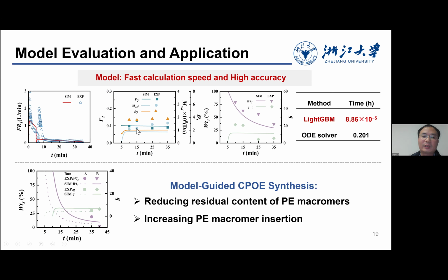You can see here we have a better match of the experiment, and the calculation results also include the molecular weights and their dispersity. And here is the weight of the residual macromonomers, and this is the insertion number of the branching chain. So finally, with this model-guided POE synthesis, we can reduce the residual content of the macromonomers and also increase the macromonomer insertion. By doing this, we can control the POE chain structure to get a higher performance.